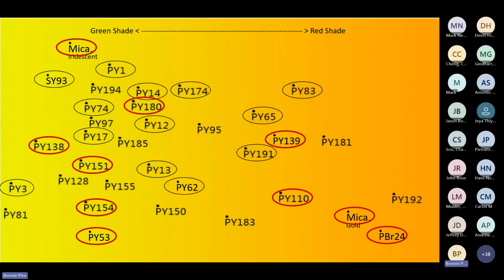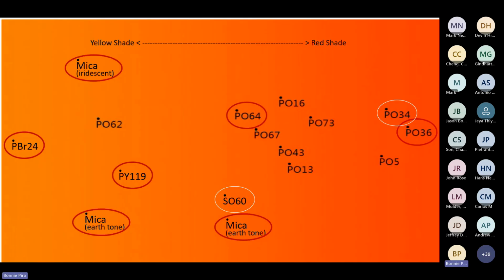So in the color space, the high performance pigments do fulfill the full color spaces. In this particular yellow color space, I have a number of color indexes on here. The red bold ones are the high performance pigments, and there is both the organic and the inorganic on these slides. So on the green side, you've got a pigment yellow 138. That's one of the most green shade in that one. And then on the inorganic side, you have pigment brown 24, which is the most red shade for the yellow color space. In the orange color space, again, the pigment brown 24 kind of straddles both color spaces. So in the orange space, it's going to be the most yellow, while the pigment orange 36 is going to be the most red.